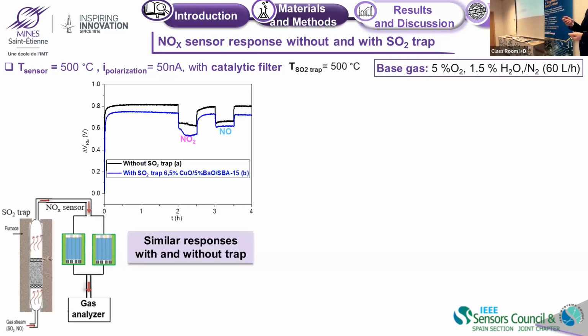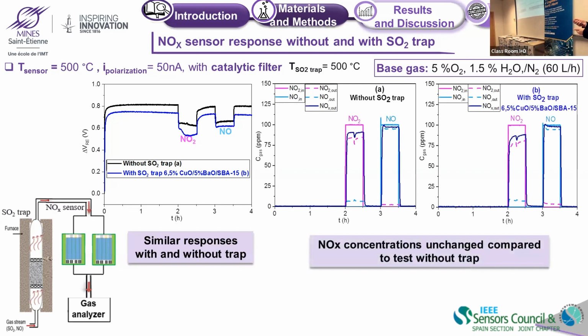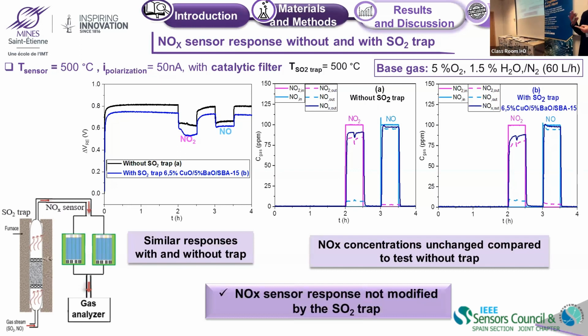Now we add the trap and do the same test in order to see if there is an influence of the trap on the NOx response. The trap is working at 500 degrees also. We can see that with or without the trap, the responses are similar for NO2 and NO. Here I show you the gas analysis responses: NO2 in pink, NO in light blue, and the total NOx in dark blue. Without and with the trap, there is no change in NOx concentration from the addition of the trap. So the NOx sensor response is not affected. And it's a good point, because if NOx was stored by the trap, the study would be finished.